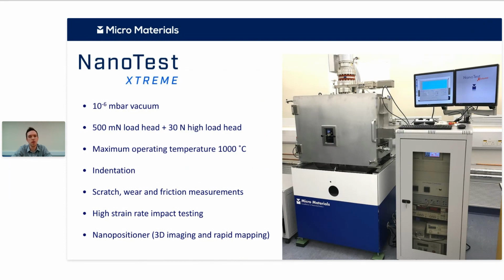So we had a brief introduction in the previous talk. In a bit more detail, the Nanotest Extreme is Micro Materials' multifunctional nanomechanical test platform that is designed to test at high temperatures in a high vacuum environment. With this system, we have two loading heads. So we can apply forces up to 500 millinewtons with the low load head and up to 30 newtons with the high load head. Both of these can be installed on the same system, so we cover the nano range and the micro range.